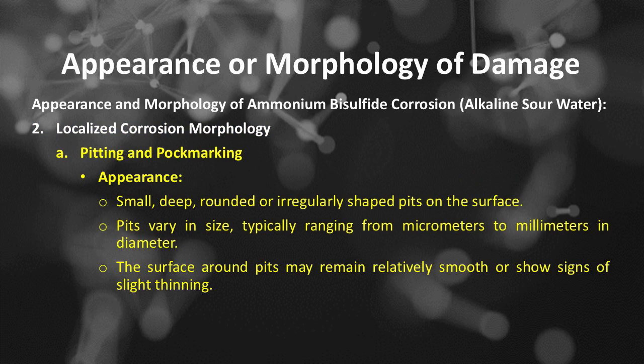Number A of the localized corrosion morphology is pitting and pockmarking. The appearance of pitting and pockmarking includes small, deep, rounded or irregularly shaped pits on the surface. Pits vary in size, typically ranging from micrometers to millimeters in diameter. The surface around pits may remain relatively smooth or show signs of slight thinning.